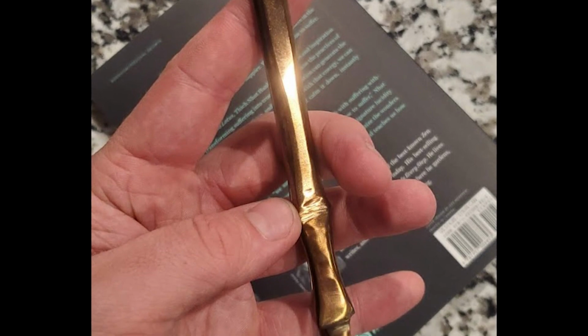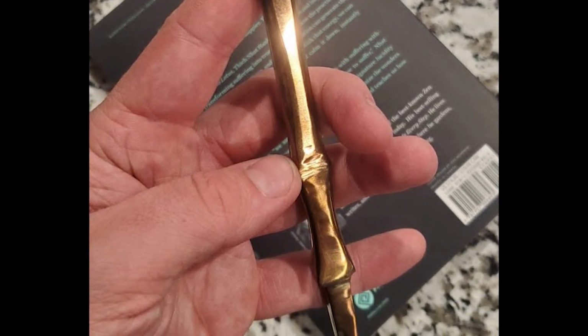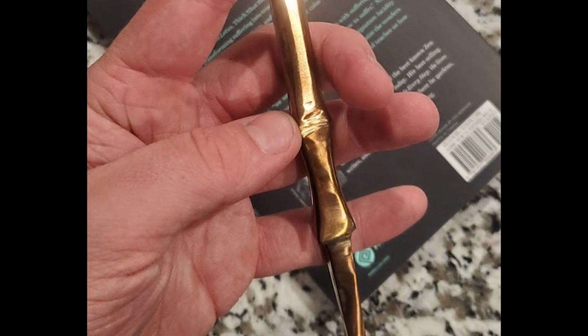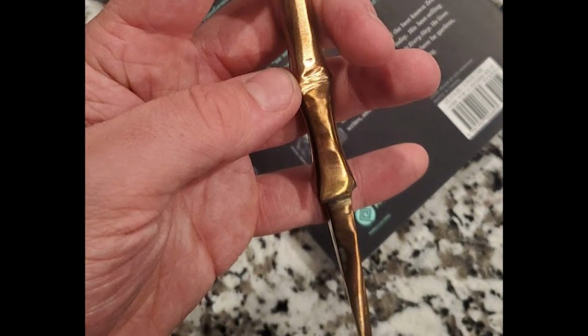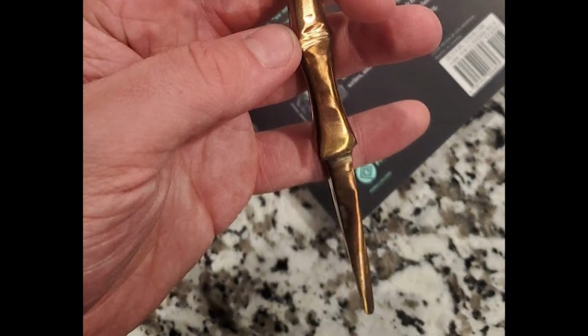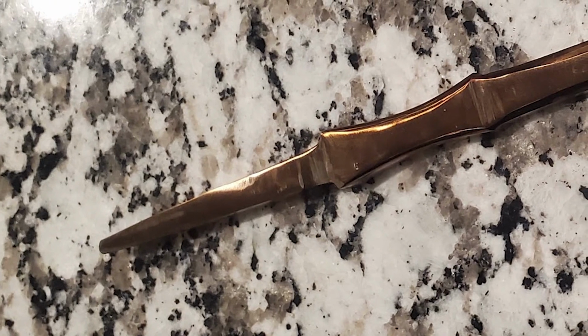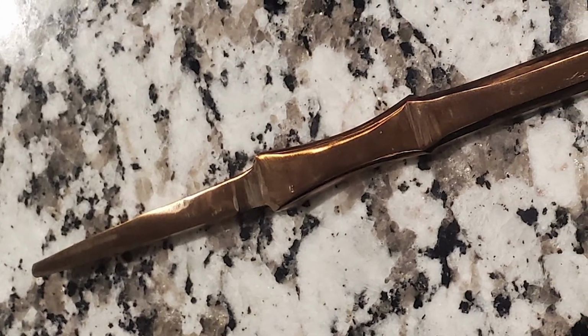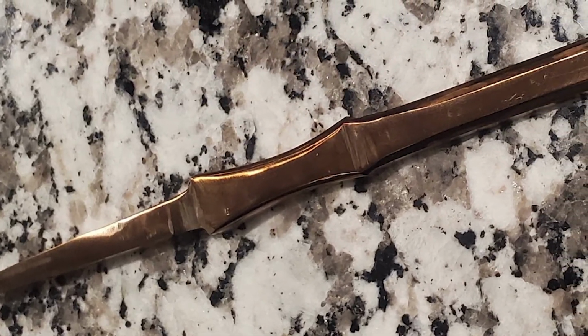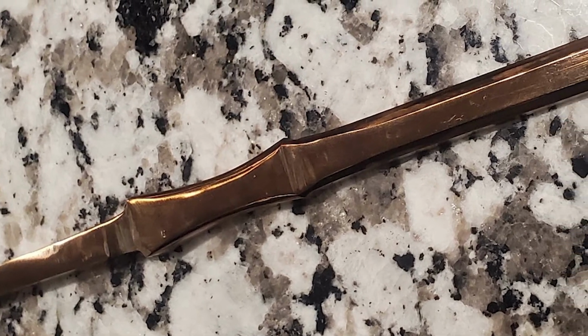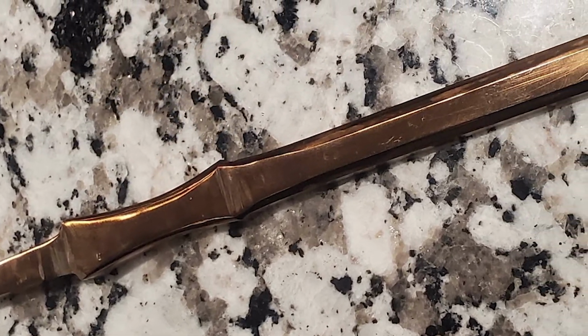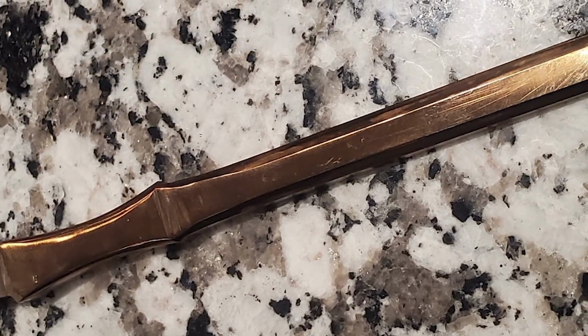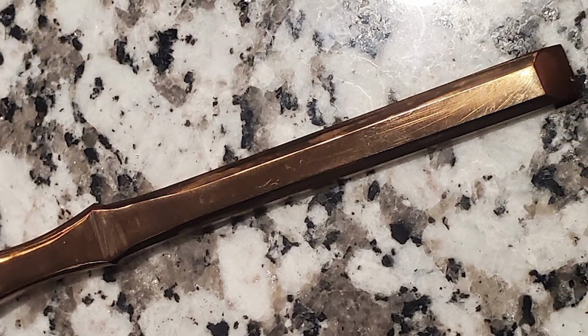In the meantime, last step, do some tempering of the steel at 420 degrees to give it this lovely hay yellow tone and soften the steel back down from the Rockwell hardness that it was before, 60 plus. This gives me enough strength in the steel to where it looks the way you want it to, behaves the way you want it to, and is at considerably less risk of snapping off in your hand. I also like the color.